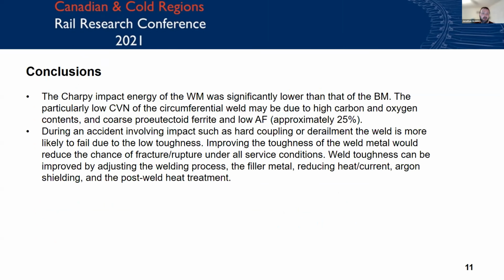So moving on, the conclusions from these tests were that the Charpy impact energy of the weld metal was significantly lower than that of the base metal. The particularly low CVN of the circumferential weld may be due to high carbon and oxygen content and coarse pro-eutectoid ferrite, which, given the time, I didn't spend much time on. I concentrated on the acicular ferrite, which we think is the leading cause. During an accident involving an impact such as hard coupling or derailment, the weld is more likely to fail due to low toughness.